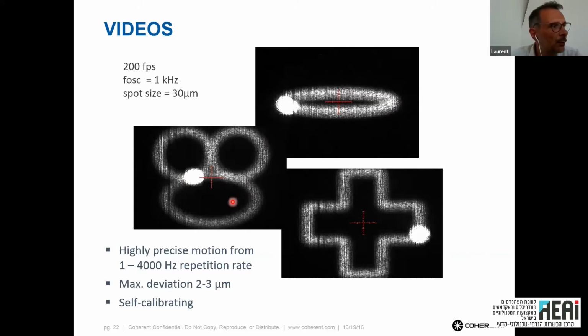Again, to give you an idea about what we are able to do, this pattern is used to weld specific stainless steel with some coating on top. It could be zinc, for example, only a few microns of zinc. It's very helpful because the two circles in front of the big one help to vaporize the zinc, and you are really able to weld with the bigger ring. It's a tricky thing, but at the end, it works perfectly.